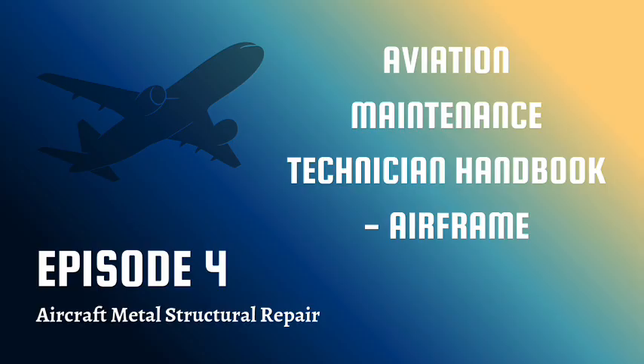And if a fire does start, what do you use to put it out? Critically, never use water, foam, or CO2 extinguishers. Water on burning magnesium reacts violently, produces hydrogen gas, and can cause explosions. Wow. Okay, so what do you use? You need a Class D extinguishing agent specifically for combustible metals. Things like dry talc powder, dry sand, calcium carbonate, or powdered graphite work by smothering the fire, cutting off the oxygen supply. Apply it gently but thickly to cover the burning material completely. Got it. Handle with extreme care and have the right extinguisher ready.